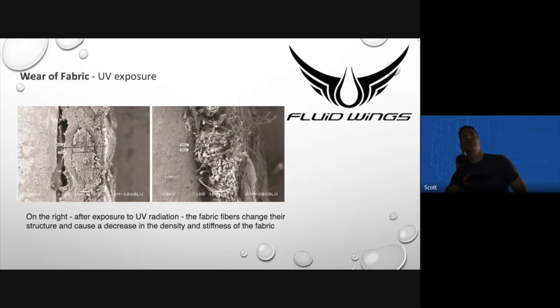This is a scanning electron microscope picture. I didn't take this. This is taken from a wear study. Some scientists at Harvard did some wear analysis on paragliding fabric, and they wrote a paper on it. And the last two slides, the slide of the close-up of the weave, and this, are both out of that paper. You can see on the left, it's a robust fiber. It's fully intact and pretty solid, right? And then if you look over on the right, that's the part of the fiber that